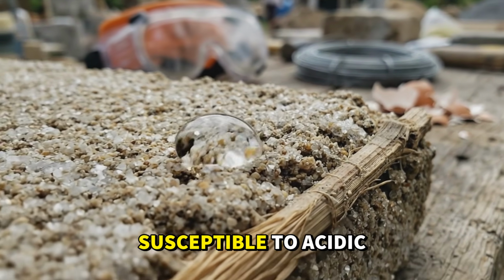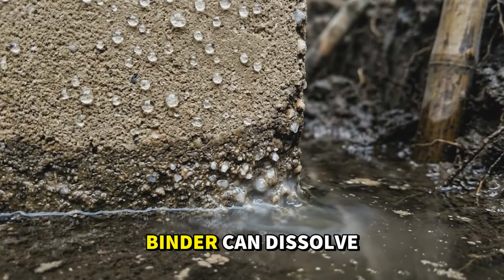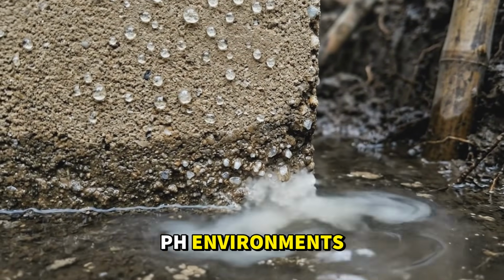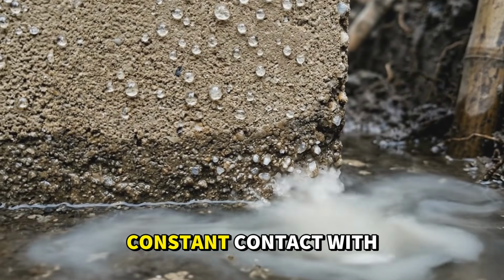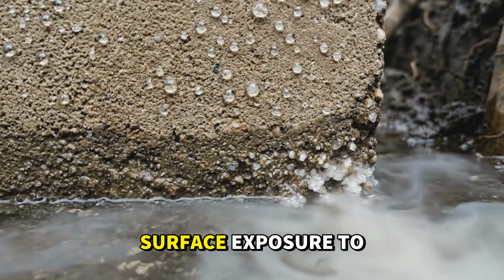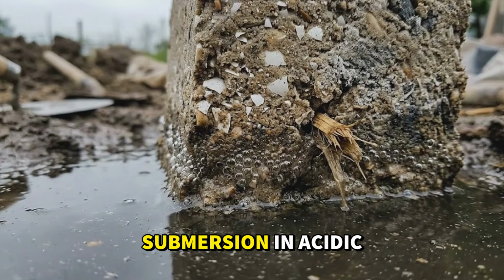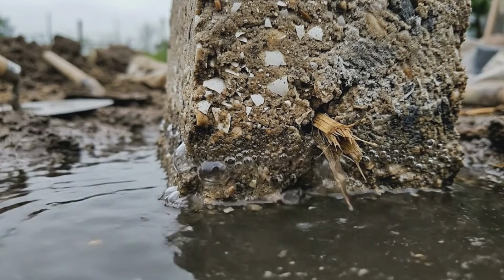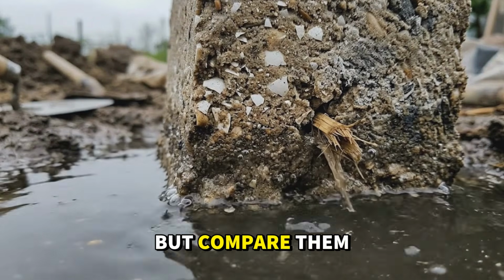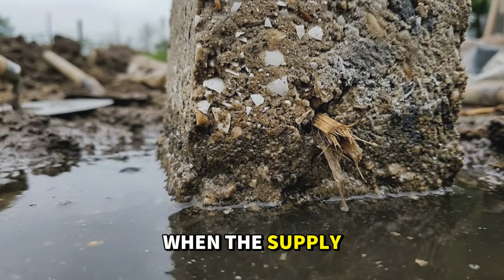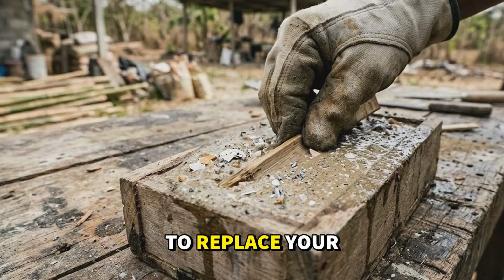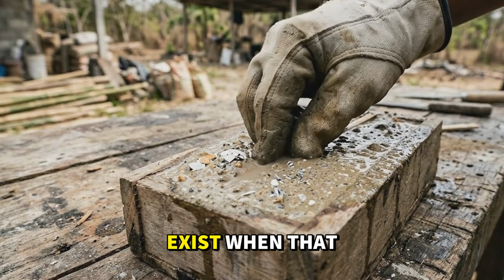Calcium carbonate is susceptible to acidic water over time. The binder can dissolve slowly in low pH environments. Don't use this for structures in constant contact with acidic groundwater. Surface exposure to rain is fine. Submersion in acidic water is a problem long term. These are real constraints, but compare them to having no building material at all when the supply chain is gone. This isn't meant to replace your local concrete plant. It's meant to exist when that plant doesn't.